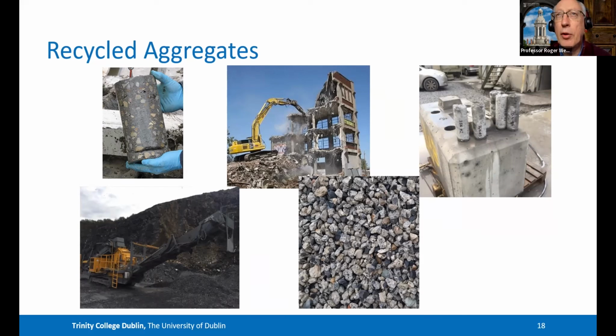And similarly, for concrete that's not used, the waste that is brought back from site, to develop the habit of making 30, 50, and 70 megapascal formwork and pouring the concrete in, coring it to make sure it's the right strength, and then having high-grade material to use.